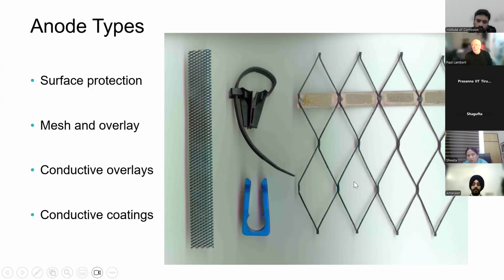And as a consequence, it would stop passing current. By putting this mixed metal oxide layer on, it can continue to pass that current for a very, very long time. And it's available in all manner of different forms. Those, the black and the blue plastic units, are just clips that are used to clip ribbon, such as on the left, which is a small version of that on the right. Clip it directly to bars in new construction, because there is no reason on earth not to put cathodic protection in new structures. Not done a great deal outside of perhaps places like the Middle East, where they have very saline water and it's difficult to get sand even for concrete making that is free of salt. But generally speaking, they tend not to get used as much as they could be.